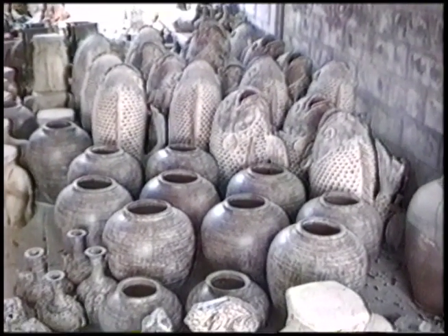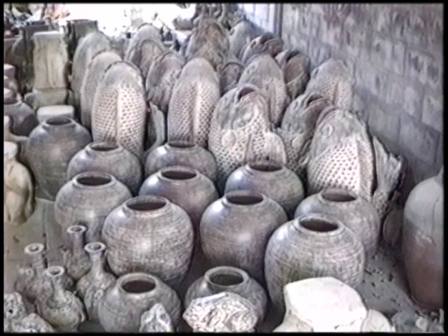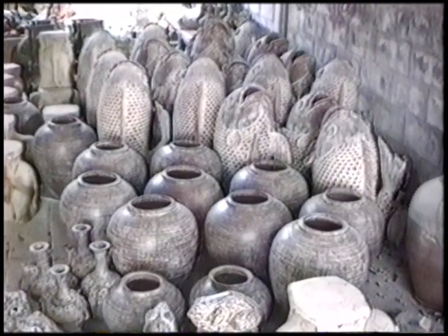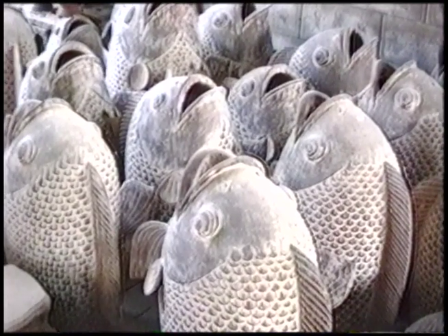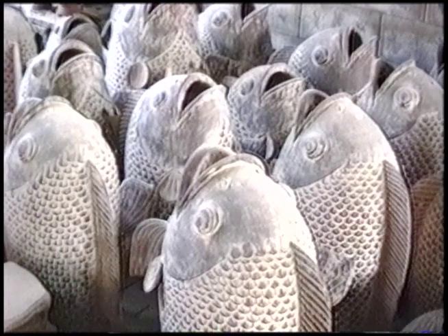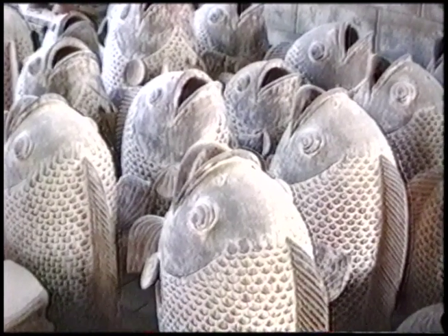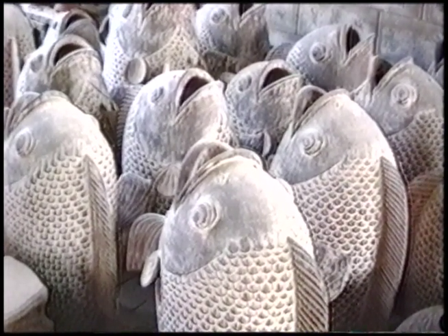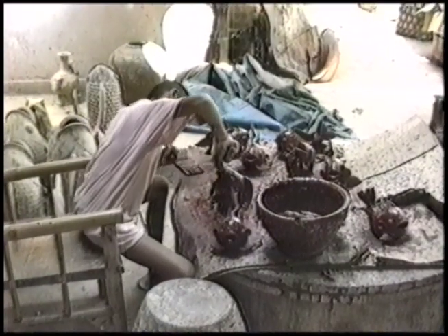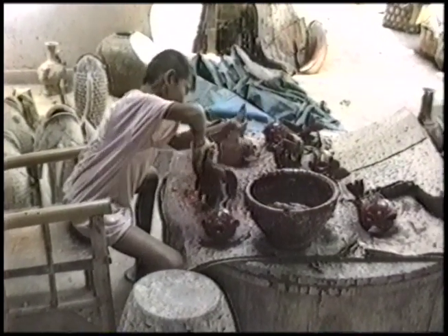Most pottery in Dan Kwian is cold finished. Fired to about 1050 degrees Celsius, it is coated in house paint, followed by a concoction of paint, dirt, and cement. Then it's laboriously sanded and then coated again with a clear finish. It is sold at Pier 1 imports across the U.S. and at import shops across the globe.